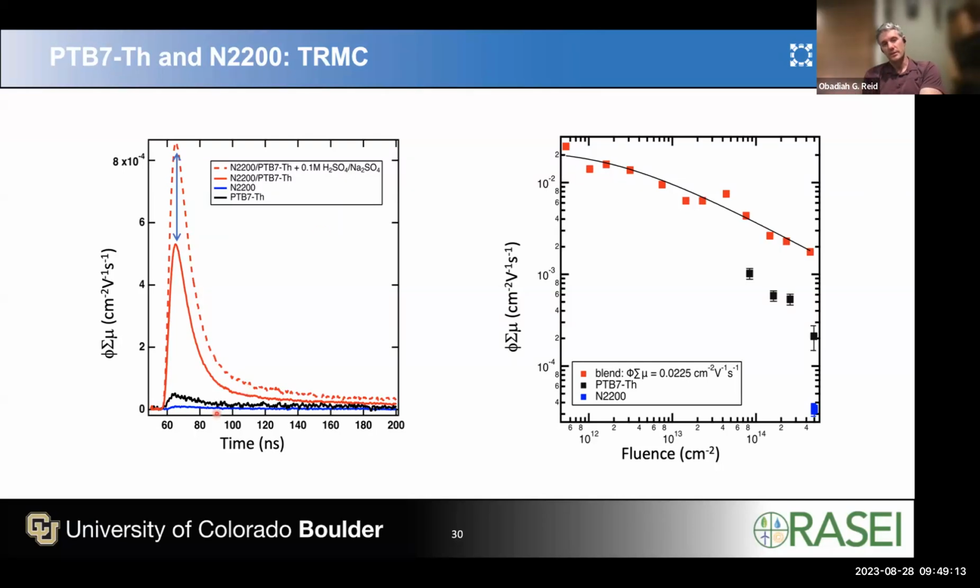We haven't had a chance to do that in TA yet, but like I said, one of the things that Abhishek and Aniruddha and I have been working on for the last couple of weeks or more, it's hard to keep track, is trying to do this more in situ. Because the initial experiments we did in the same ex situ way I described, where we would take the film, put it in the acid solution, take it out, shake it off, and then put it in a saturated humidity environment to do a microwave measurement.